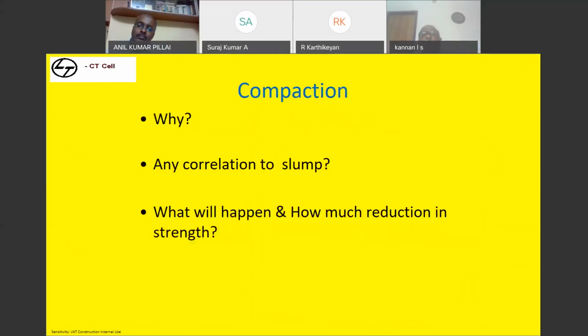When it comes to compaction, why do we need to compact concrete? Compaction of concrete is essential to remove the air entrapped in concrete. And is there any correlation to slump? Yes. Higher the slump of concrete, you have to compact it less. Lower the slump of concrete, you have to compact it more. The reason is when you are compacting it, the concrete is going to move. So if it is fluid concrete, you should not compact more, it will segregate. Lesser slump concrete, if you are not compacting well, it may not flow. So depending upon the slump, the compaction time also needs to be verified.